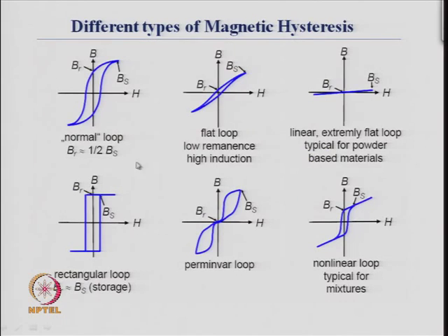Now, you can have different types of hysteresis. You can have a hysteresis loop which has a very small area, and here the area is large. Then you can have a hysteresis loop where you have a nearly very sharp change in the magnetization or magnetic flux density, or you can have a smooth change in the magnetic flux density. So, there are different types of magnetization as shown by these 3. Here the remanence is very low, here the remanence is very high, this also has a very high remanence, okay. But you reach saturation very fast, the moment you cross this field you immediately reach saturation.